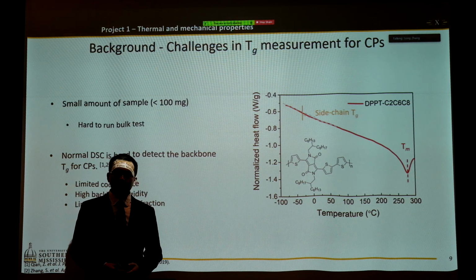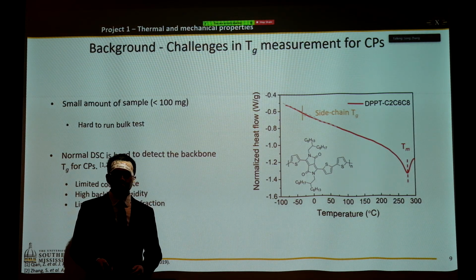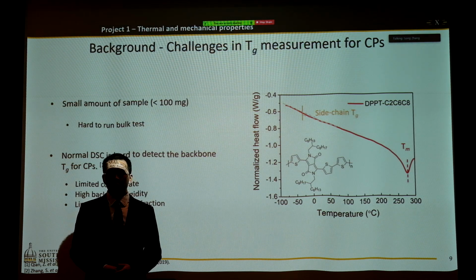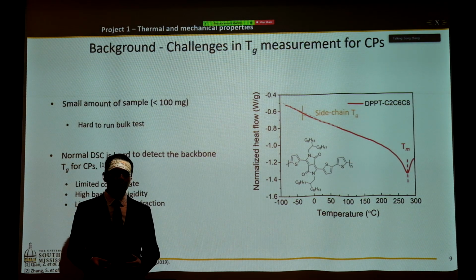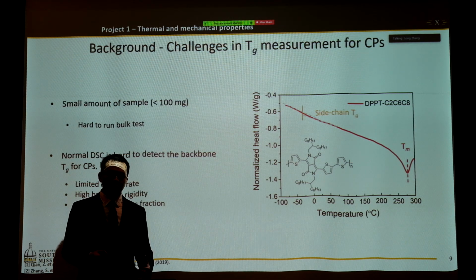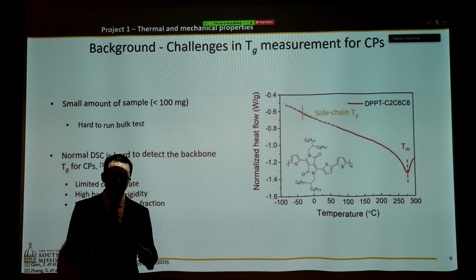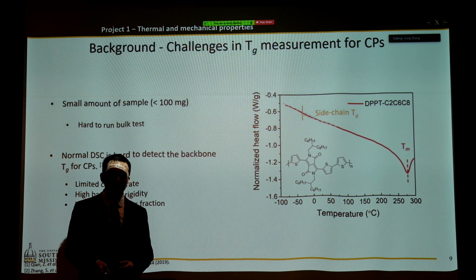So what about using a traditional DSC? As shown on the right-hand side, this is a typical DSC curve for a DPP polymer. However, now we can only see the side chain Tg and melting behavior. And the backbone transition is very smeared in between these two temperatures.